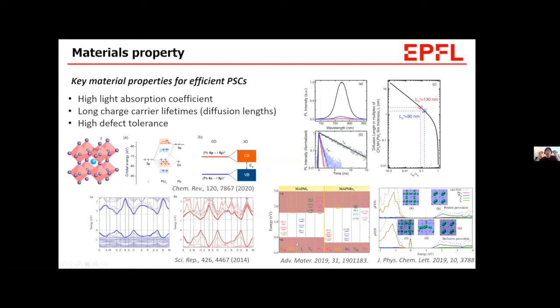It somehow, by interacting with these halides, the trap states or orbitals can be repelled from this band gap. If you have states in between here, for example, we call it a deep level trap, which is very detrimental to device performance.